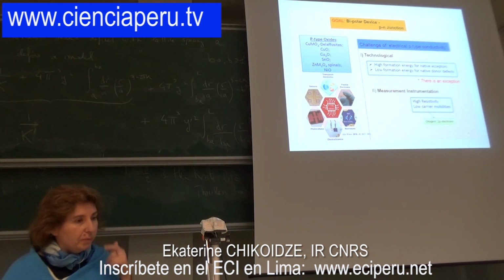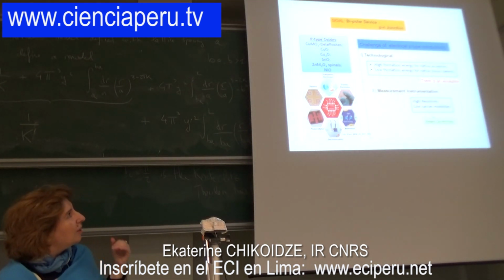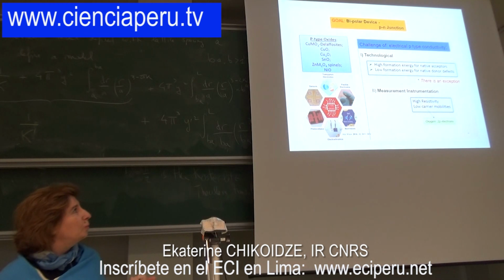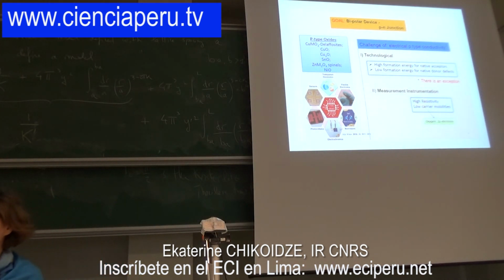So I would like to make this clearer, so I divided it into two parts: what is really the challenge of oxides for conductivity. One I can call the technological challenge to fabricate P-type materials. As I said, the difficulty is the high formation energy of native acceptors. It means that to create an acceptor we need a lot of energy, and the material creates an obstacle to this, so it's very difficult to create acceptors.